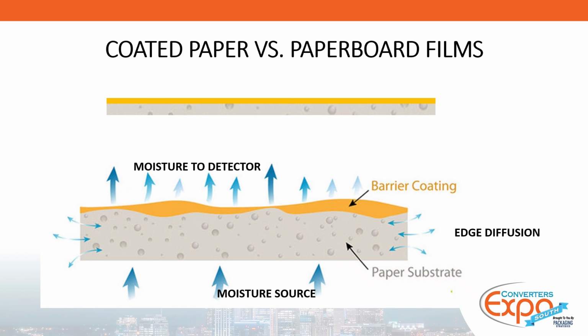And with a much thicker substrate, as you can see in this drawing here, these arrows represent what we call edge diffusion. And the bigger the surface area is, the more pronounced potentially this edge diffusion, whereas you have your moisture source on one side, and as that moves into the film, that moisture, say, for instance, 50% relative humidity, moves into the substrate, some moves out of the edges, and then the rest will move through the film and be measured.